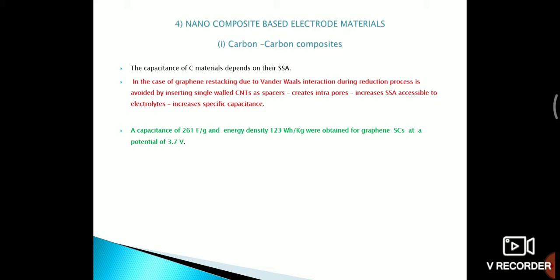And the capacitance of 261 farad per gram and energy density 123 watt-hour per kilogram were obtained for graphene supercapacitors at a potential of 3.7 volt.